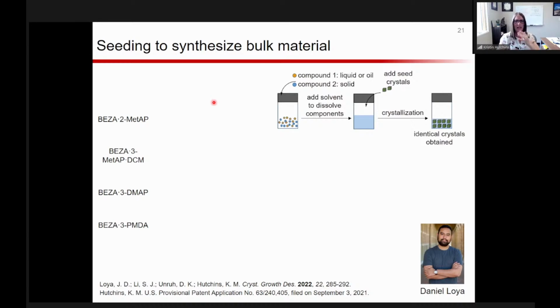And so with this case, what we did is we took our liquid pyridine and our solid, we dissolved those in solution, and we took those crystals that we had in hand from the milling and slow evaporation path, and we just added 1 or 2 single crystals to that slow evaporation experiment. And then what we were able to do was actually obtain identical co-crystals via this method that's called seeding.